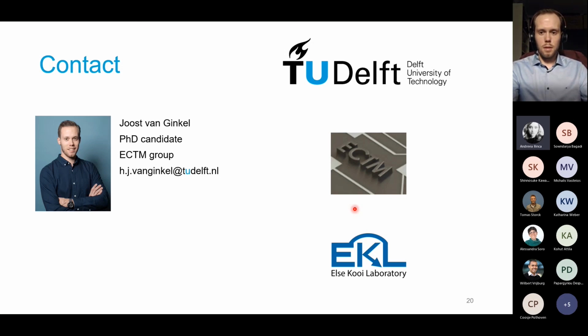We have another question. Do you have adhesion problems with the printed gold? Do you apply a protective coating after printing? Well, the adhesion of the gold to silicon oxide is known to be very bad. In industry, they use a thin layer of chrome as adhesive layer. But it's not possible to do that here because you would need to print unoxidized chrome and then gold, which is not possible with our setup.